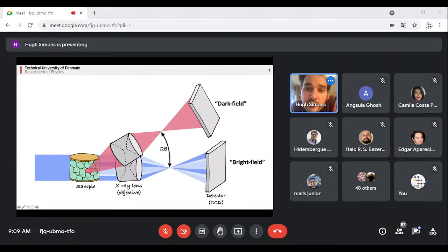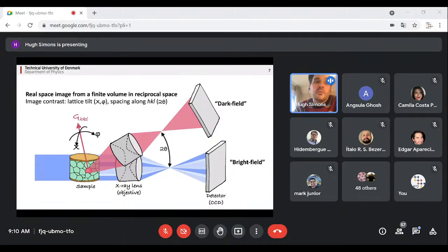So in dark field X-ray microscopy, essentially we're creating a magnified image of a single buried structure inside a material, where the contrast is given by the diffraction process. In other words, it gives us a real space image from a finite volume in reciprocal space. And this gives us intensity contrast due to the tilt of the lattice inside this grain, and also the lattice spacing along a given HKL. And so this essentially gives us lattice strain.